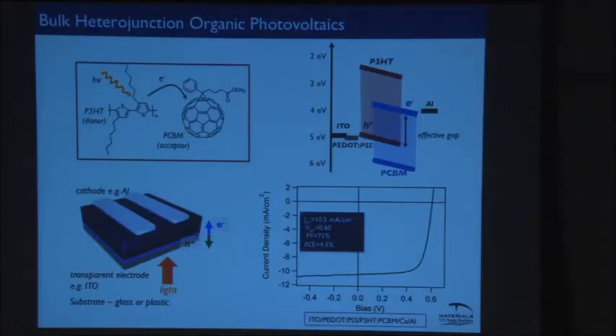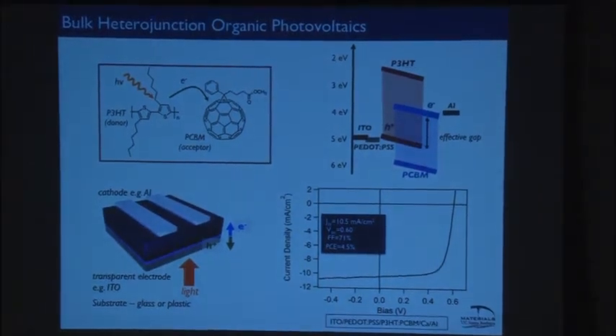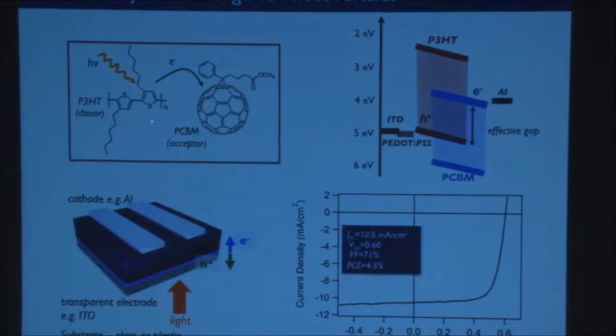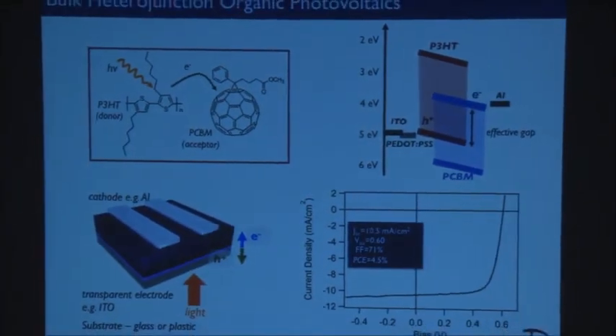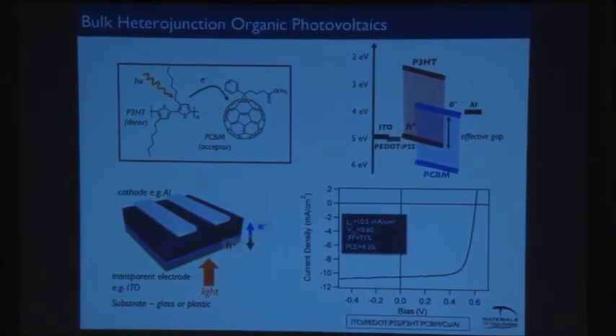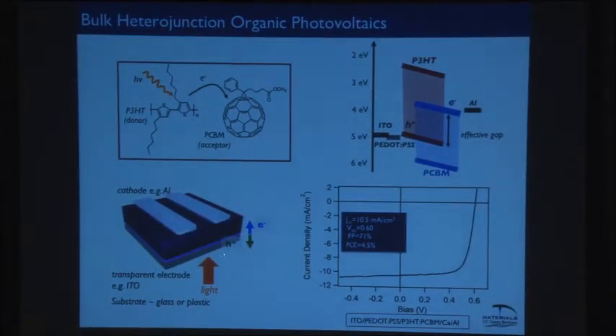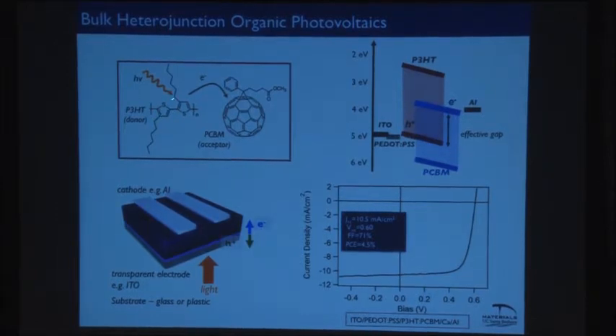So today I'll give you a sense of how these things work, because they're a bit different than conventional p-n junction solar cells. Bulk heterojunction solar cells were invented at UCSB by Alan Heeger and Fred Wudl. What they found, and they didn't necessarily intend to do this, was that they took a polymer like poly-3-hexylthiophene, mixed it with a fullerene in solution, and cast a film of it. They put an electrode layer on the bottom where one contact has an electrical level such that it can accept holes. It's lined up with the highest occupied molecular orbital, or valence level, of one of the materials.